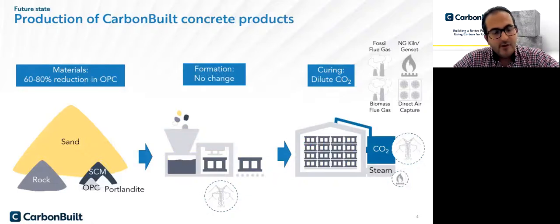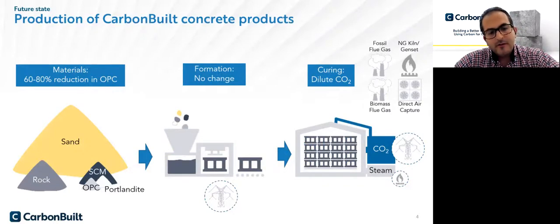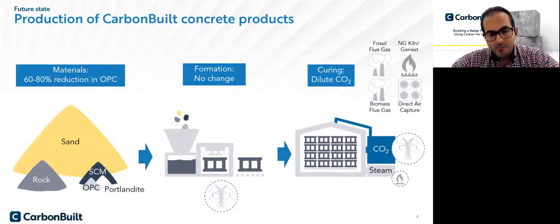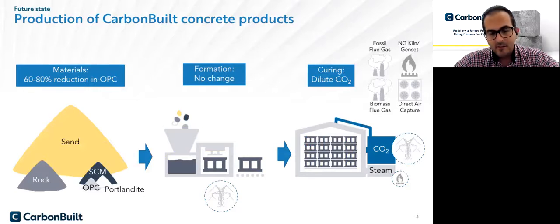During the CarbonBuilt process, we substantially displace cement with supplementary cement materials that can react with carbon dioxide, like portlandite. We also use portlandite during this process — they mix together and undergo the same manufacturing process. After that they are placed into the curing chamber, but we use diluted carbon dioxide to cure and harden the concrete material. The source of this diluted CO2 could be from fossil flue gas, biomass flue gas, or even modular direct air capture. The key feature of this process is it doesn't require any concentrated carbon dioxide, high temperature, high pressure, any carbon capture step, or any purification.